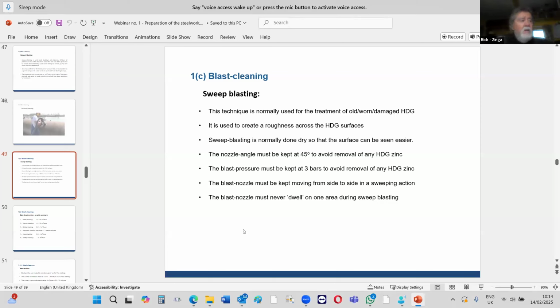We've had some guys phone us and say, we had these galvanized beams, big beams, they weigh 5 tons each. They were hot dip galvanized, and we checked on site and they're sub-spec. Hot dip galvanizing is normally around 83, 85 microns, and these beams were 60, 62. So same thing, sweep blast, and then spray on the Zinga, and it builds up. On hot dip galvanizing, sweep blasting is used for repairs and for increasing the film thickness of the galvanizing.